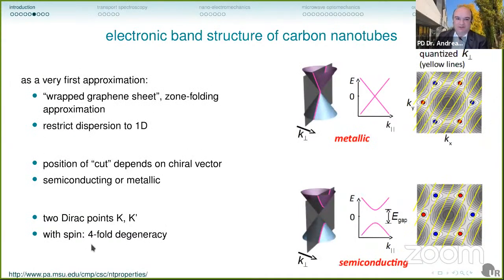On the electronic side, explaining the structure of carbon nanotubes nowadays is pretty easy because everybody knows graphene. So everybody knows these Dirac cones of the dispersion relation of graphene. And if you take, as a first approximation for forming a nanotube, a graphene sheet and fold it together, wrap it into a tube, then you can impose periodic boundary conditions onto the dispersion relation of the graphene. You make one-dimensional cuts through this plane, like the yellow lines here. And depending on how you exactly wrap up your sheet, you either hit the Dirac points, then you get a metallic nanotube, or you don't, and then you get a semiconducting carbon nanotube. You have the same two Dirac points as in graphene, two non-equivalent Dirac points, and thus electronic states can have, together with the spin, a fourfold degeneracy.